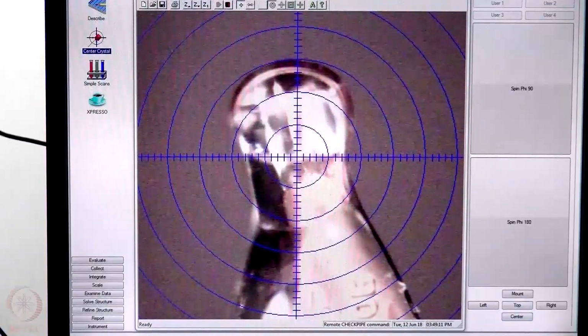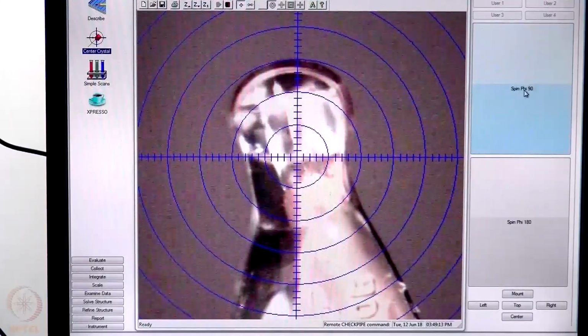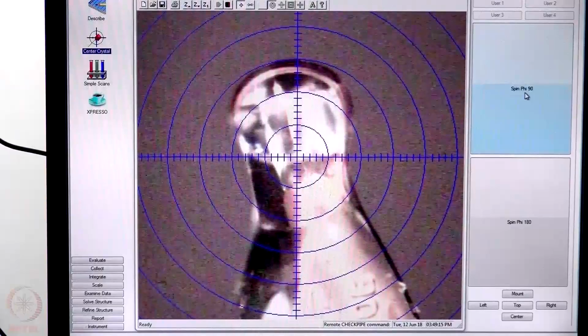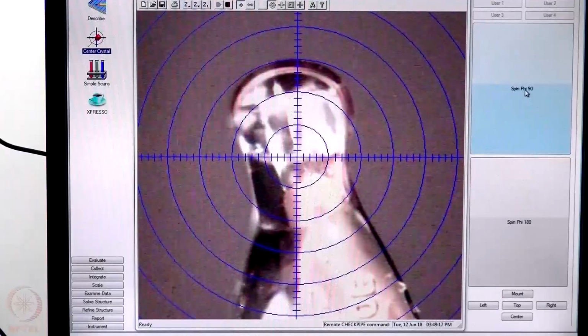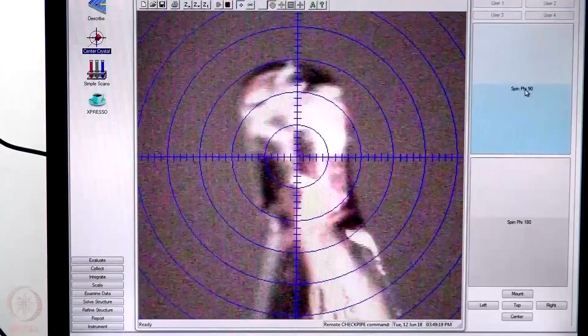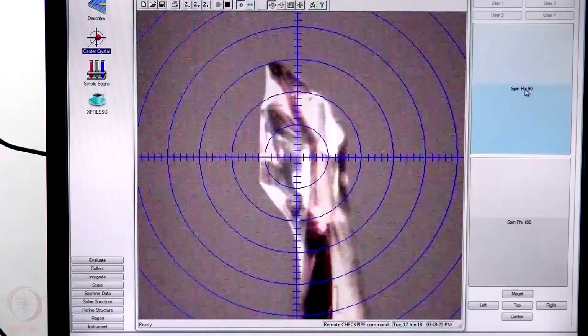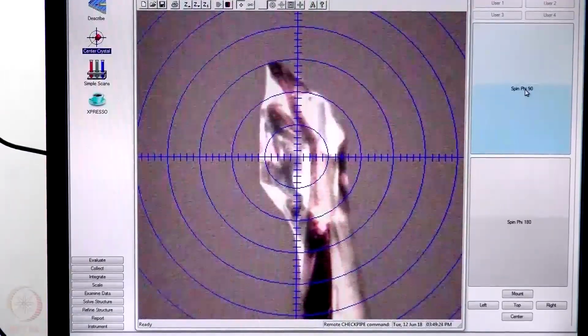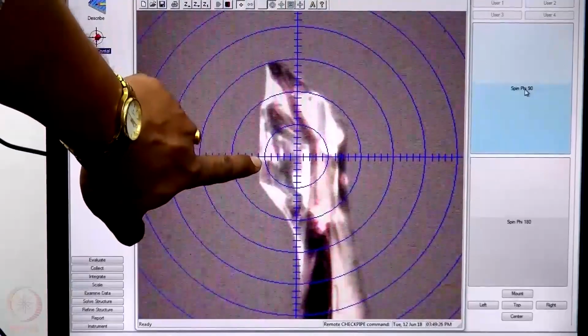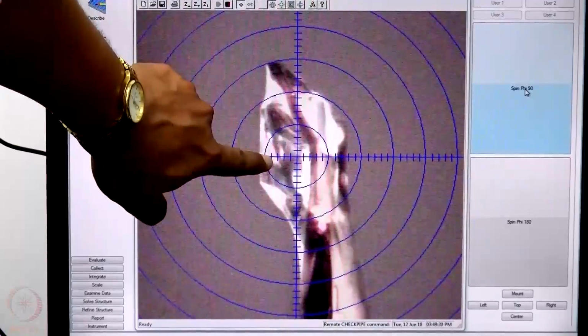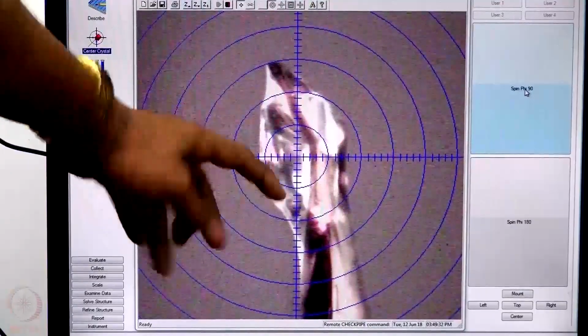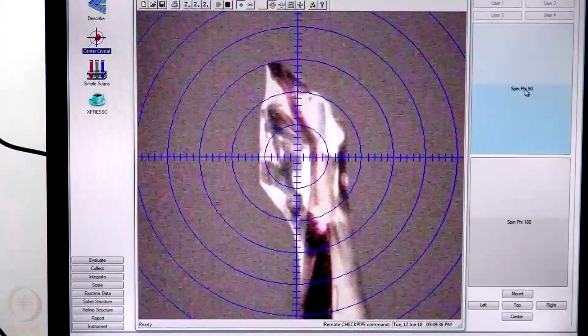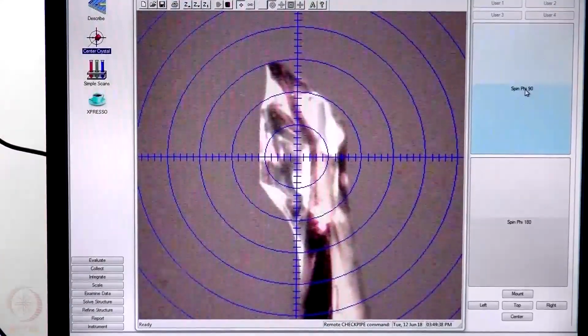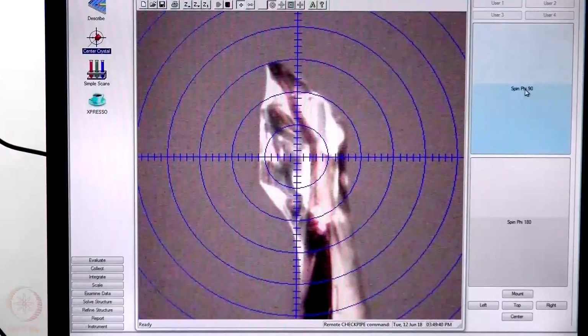Then we need to see what has happened to the 90 degree with respect to this. Now we can see that the crystal is in between two reasonably centered locations, and from the top and bottom, so the crystal is here and between these 2 points at this 90 degree location. So I rotate the crystal by another 90 degree.